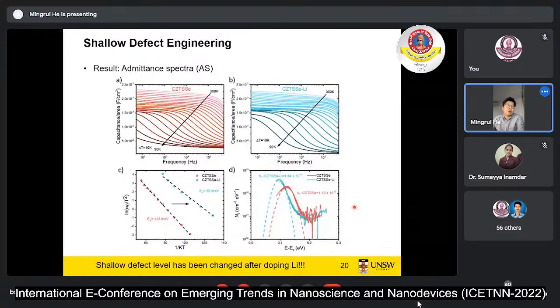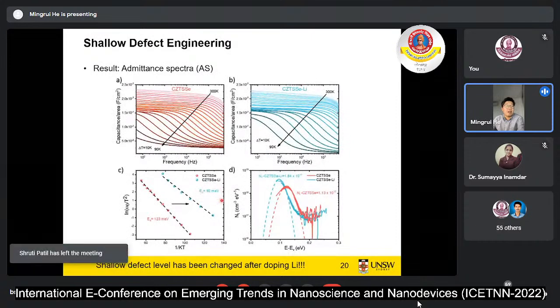But we don't know why. According to the literature, where they did some DFT calculations, we know that if the activation energy is around 100 something or 120 something, it corresponds to the copper zinc anti-site defect. So we don't know what the defect is for the activation energy around 90 something.